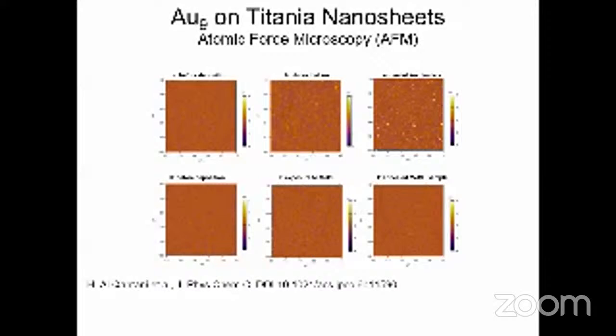After annealing, we remove the ligands at 200 degrees for about 20 minutes, and we make sure we are not having any phosphine. We confirm that by XPS, where we don't have any peaks of phosphorus after we annealed and removed the ligands itself.